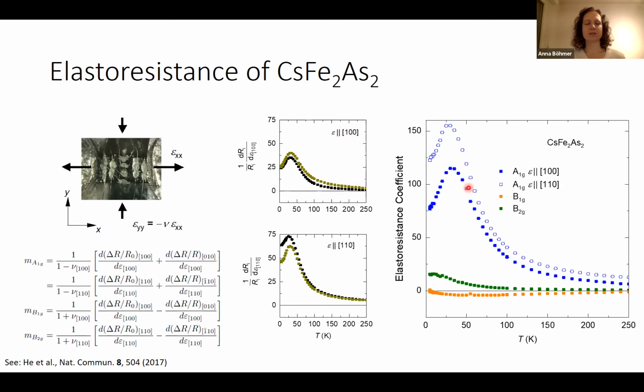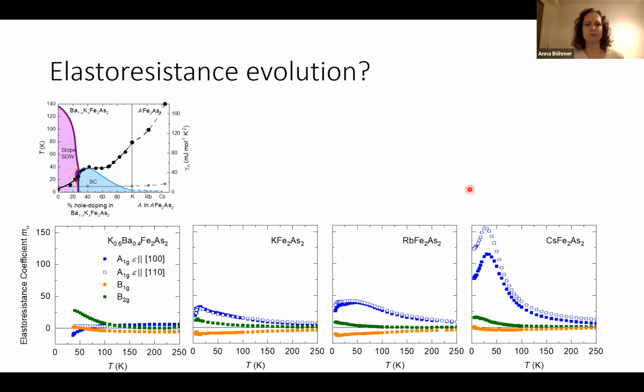That was our first result. And secondly, we went to the evolution of this. We go again over this phase diagram from somewhat optimally doped to the pure potassium, rubidium, cesium. In this one, which is still close to the stripe-type order, we see an increase of the B2g elastoresistance, very similar to what we just had. We have small A1g and B1g components.